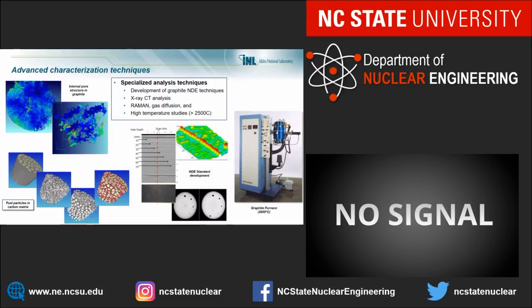One of the things that is really important is NQA-1 quality. That is Nuclear Quality Assurance Class 1. Extremely important. If you don't have NQA-1, you can't put this in a nuclear reactor in this country. Okay. So we deploy all sorts of techniques: NDE techniques, X-ray CT tomography, Raman. A lot of our studies are performed at higher than 2,500 degrees Celsius. This furnace, for instance, which looks like one I saw in one of your labs, functions at 2,800 degrees Celsius.